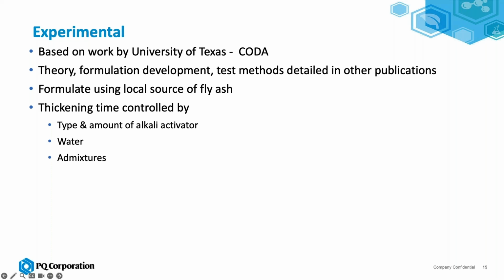From there, it was modified to suit the needs of the operator as well as the local source of fly ash. The way the thickening times were controlled was by the type and amount of silicate. So whether it was sodium silicate or potassium silicate and the ratio or how alkali the silicate was. The other dials that could be turned were the amount of water. So water works as a retarder.